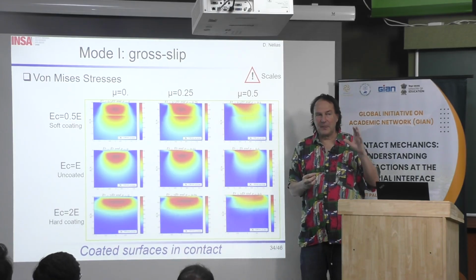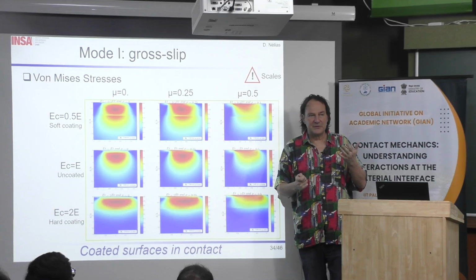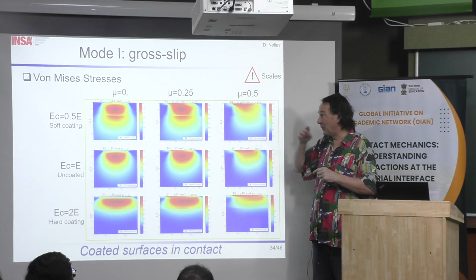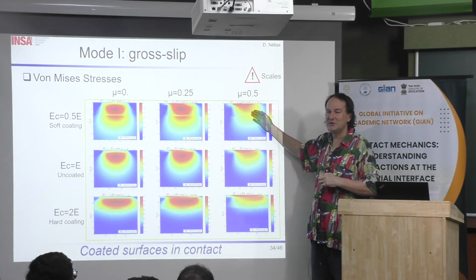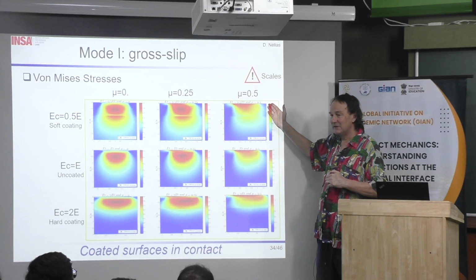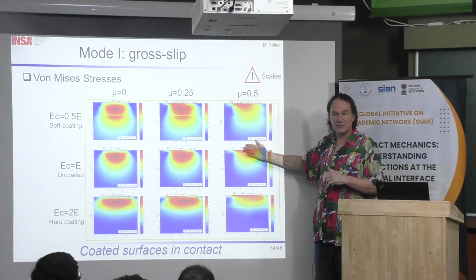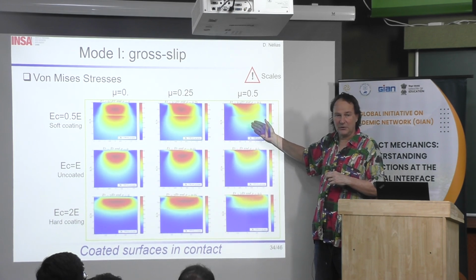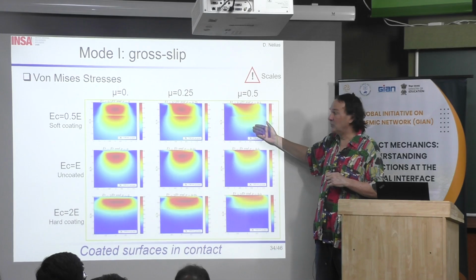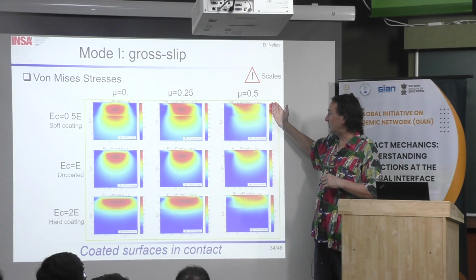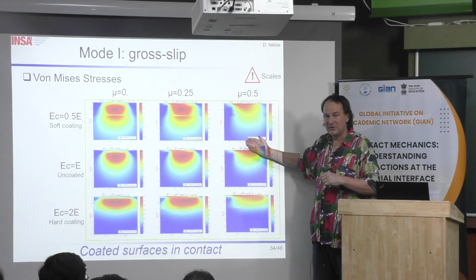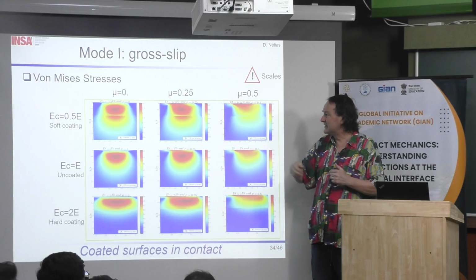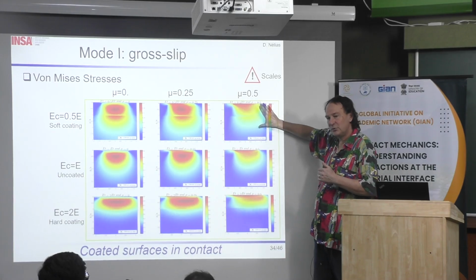But in fact, I will say that there are two optimums for the coating. The first one is when you have a gradient material. I mean with no coating, just you have some properties that are varying with depth. This is what you can do when you have a heat treatment, such as nitriding or cementing material. Then you will have something which is harder at the surface, and progressively it will be softer. But there is no interface, then there is no risk of decohesion. For me, this is the best solution, instead of a very thick coating, even a huge coating.